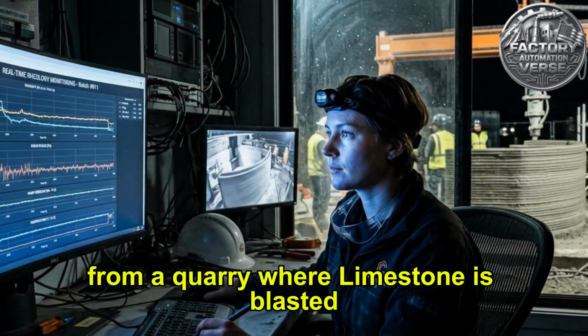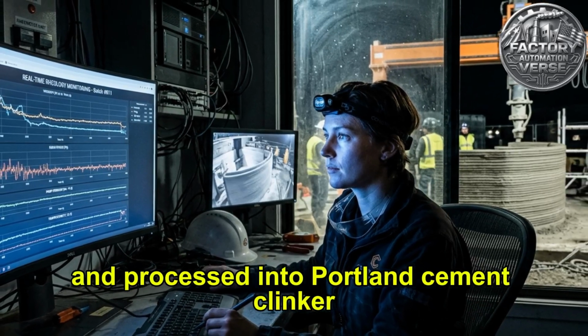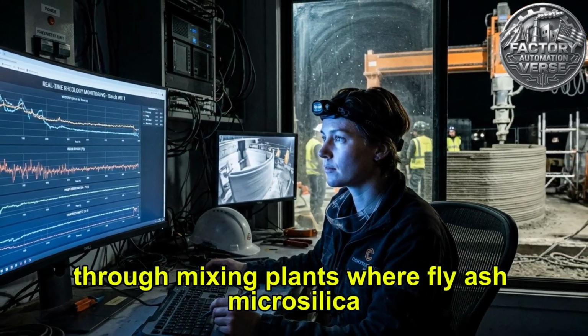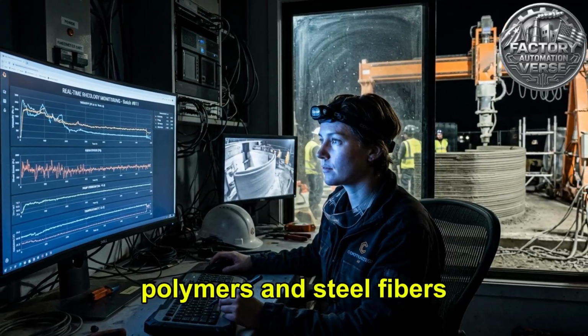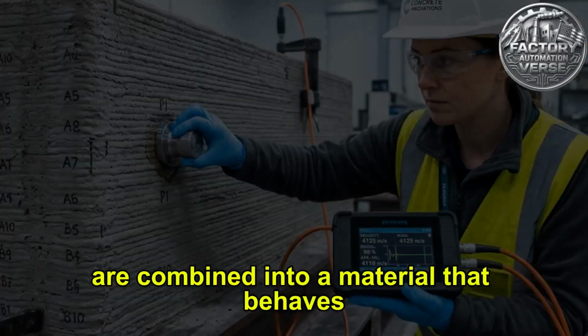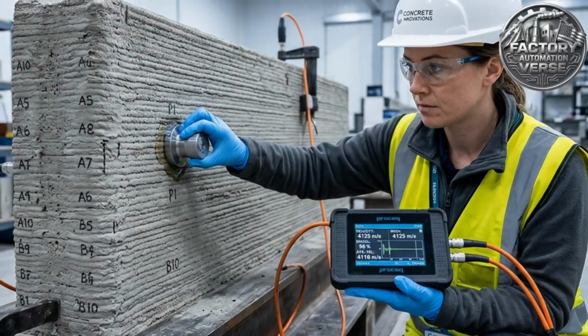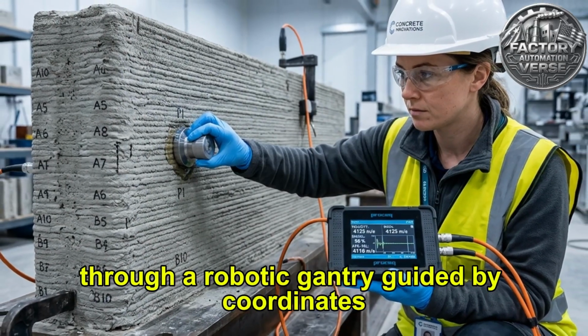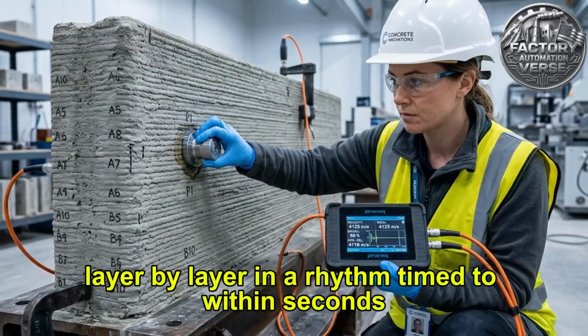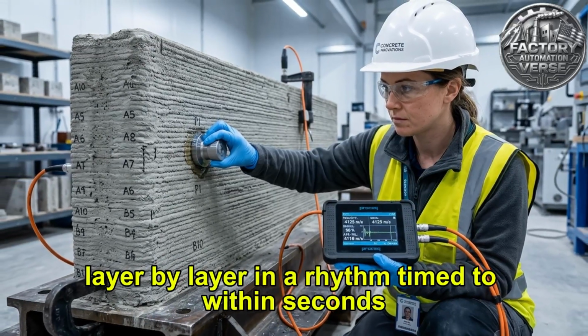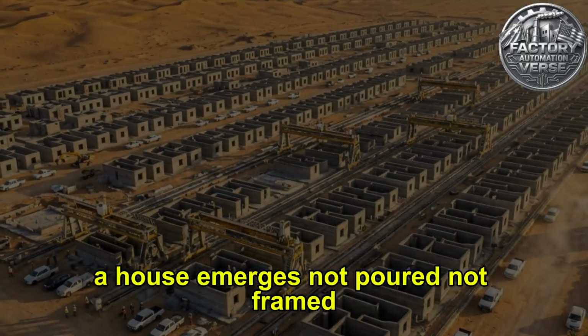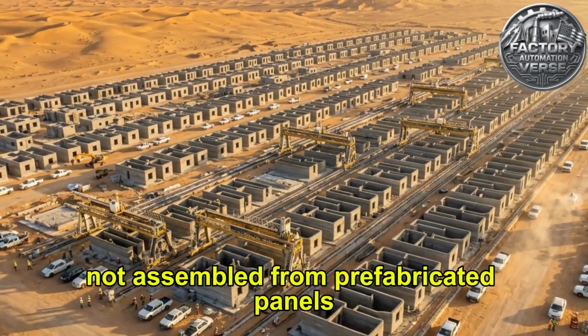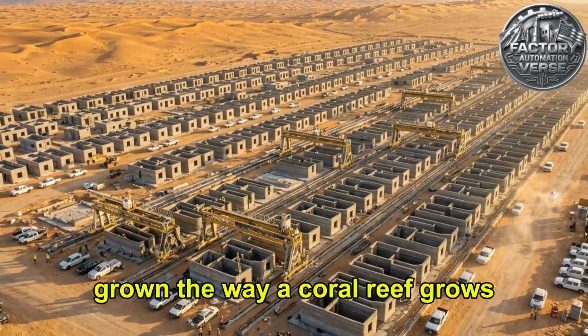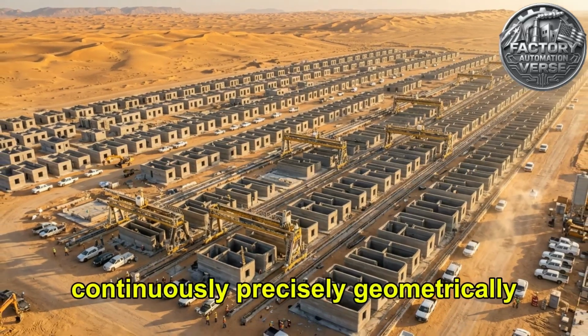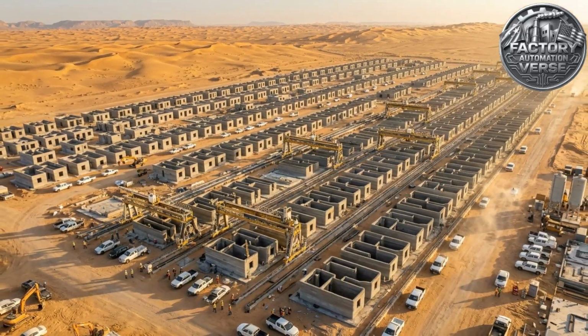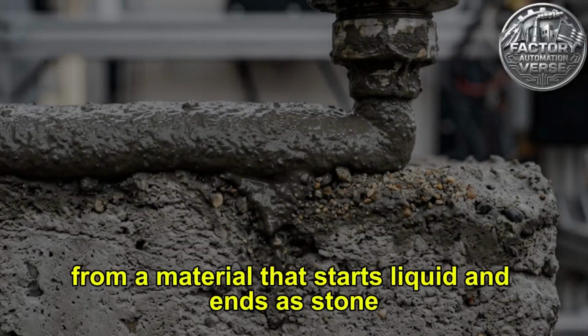From a quarry where limestone is blasted and processed into Portland cement clinker, through mixing plants where fly ash, microsilica, polymers, and steel fibers are combined into a material that behaves unlike any concrete in history, through a robotic gantry guided by coordinates generated from an architectural drawing, layer by layer, in a rhythm timed to within seconds, a house emerges. Not poured, not framed, not assembled from prefabricated panels. Grown the way a coral reef grows, continuously, precisely, geometrically, from a material that starts liquid and ends as stone.